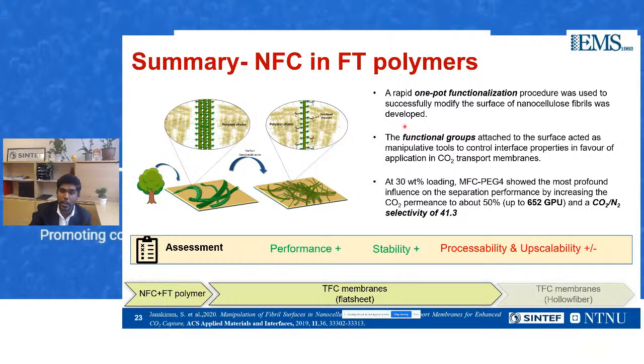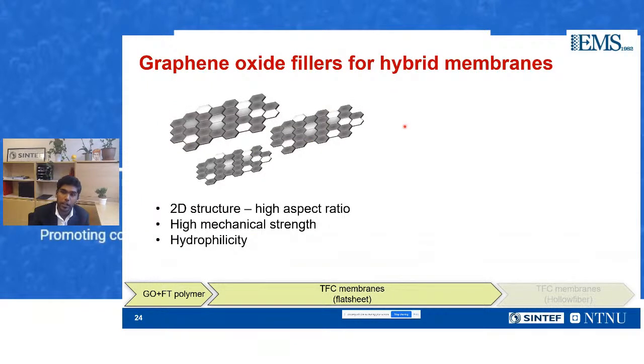So we wanted to diverge to our next friend that we thought would help us, which is graphene oxide fillers. Graphene oxide, unlike nanocellulose, is a very different system where you have a 2D structure with a high aspect ratio, as opposed to 1D in nanocellulose. But the best part is that the one dimension, the thickness of these graphene oxide fillers, is in the atomic or nanometer range, which gives us an opportunity to make very, very thin selective layers.